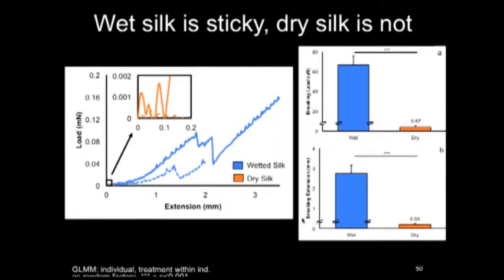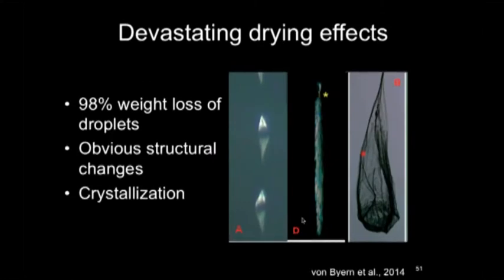And this is likely due to this drying effect, and if we look at these photos, it becomes quite apparent, where almost all of the weight due to water is reduced. We see they, in their natural condition, or after re-wetting, look quite plump and full of water, but when dried, they start to crystallize and become far less obvious and shrunken and sullen. And you can see this is the final droplet that hangs at the end of the fiber that collects the most liquid. It's become shrunken, sort of crystallized with this root-like lattice. It's not a very pretty sight, and clearly these fibers suffer from that.